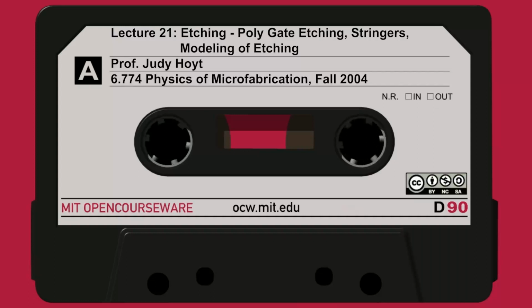So after you've removed this and you open this hole, well, then you have an open hole. You can put down your high K, your hafnium dioxide. You can put down your titanium nitride by sputtering and a tungsten cap, and then maybe some capping layer of dielectric and CMP the whole thing down. So that's how they got that last picture. That's how they got that replacement gate.